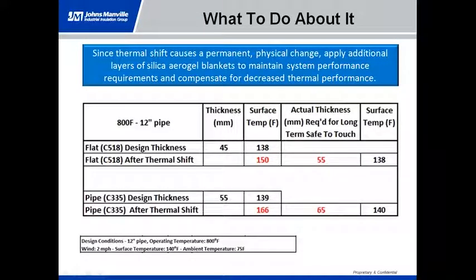Because it does cause a permanent physical change, and we do know that this happens, there's a way to work around that. Combining our first point that we talked about, round versus flat data, with thermal shifting, we can show how to get around this. If you look at our first example, it's an 800-degree pipe, and we have flat design ASTM data versus our thermal shifted data. If we use our design data, we're at a 45 millimeter thickness with a surface temperature of 138 degrees. But if we use the thermal shift data for the same thickness, now our surface temperature is 150 degrees. Now we need a 55 millimeter thickness to get our surface temperature back down to 140 degrees.